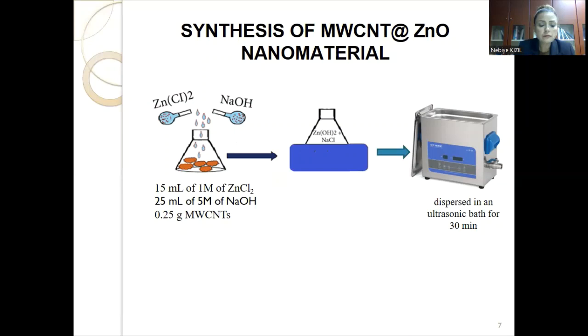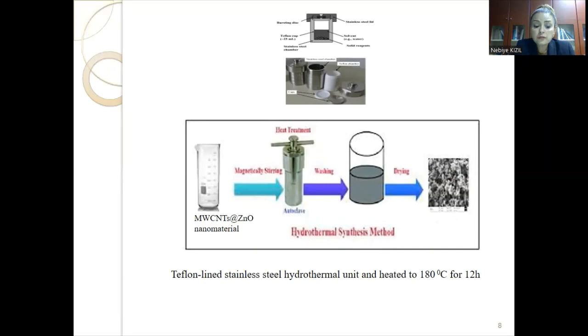Then transfer into hydrothermal unit and heated to 180 centigrade degrees for 12 hours. After this, nanomaterials were obtained and washed twice with pure water, acetone, and dried in an oven at 60 centigrade degrees.